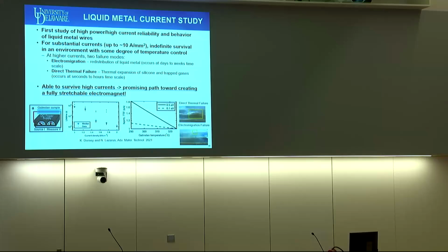And we found, importantly, that even for some pretty substantial currents, so up to about 10 amps per millimeter squared, we could get indefinite survival in environment as long as there was some degree of temperature control. It does at some point eventually start seeing some failure mechanisms. Eventually you get electromigration, so basically the redistribution of liquid metal due to the current flowing through, on the days to weeks time scale. And if you go to even higher levels, you get direct thermal failure, so the expansion of the surrounding silicone and then pinching out regions of the liquid metal. But importantly for our purposes today, the fact that we're able to survive very high currents is a very promising path toward creating a fully stretchable electromagnet.